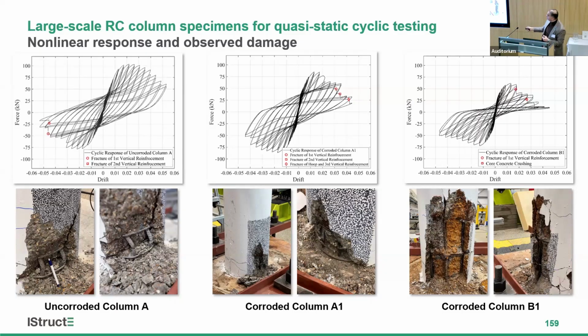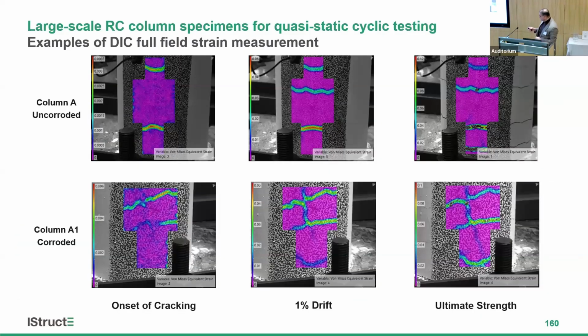So this is essentially the two fractured bars after the low cycle fatigue. And this is essentially when the bars started fracturing in tension. And these are essentially fractured, but a lot of this degradation comes from the concrete crushing. So it's a different failure mode. This is also showing in the DIC pictures.